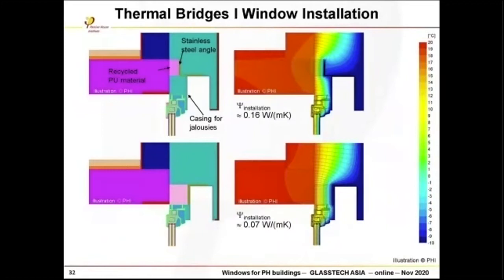Well, if you go for boxes for shading elements, the same is true. You should install the boxes as good as possible and with lowest thermal heat losses as well. And you see here below, the Psi value is 0.07, the above is 0.16, so a factor of 2 is always possible with that, just by optimizing the geometry.